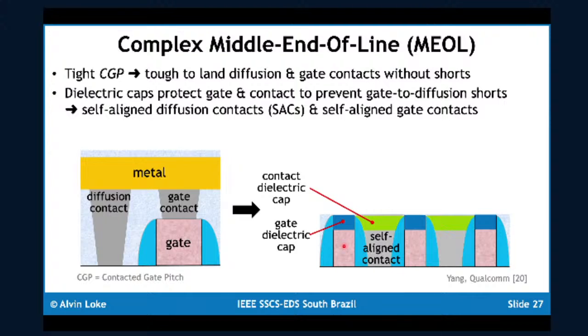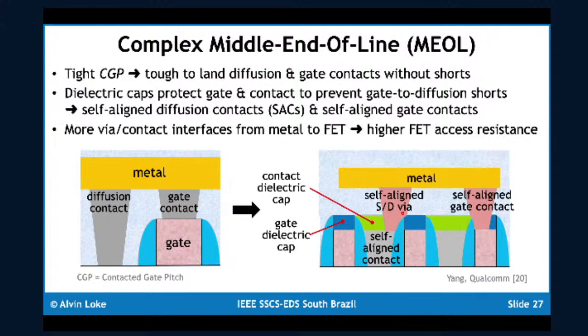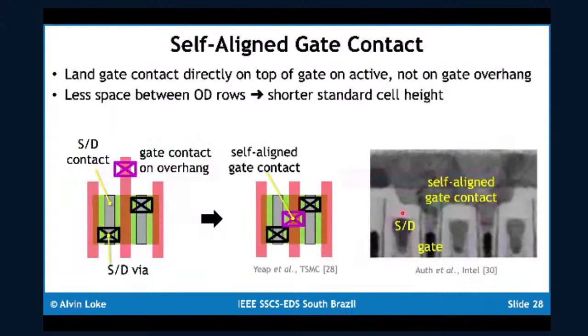Furthermore, we may need to put dielectric caps on top of the contacts, diffusion contacts, which in turn allows us to do self-aligned source drain as well as gate contacts without shorting to the other nodes. Long story short, this is a much more complex middle end of line, which is the contact modules. Accessing the transistor from the metallization above requires many more interfaces from vias and contacts, which in turn increases the FET access resistance. Just a quick look at self-aligned gate contacts here.